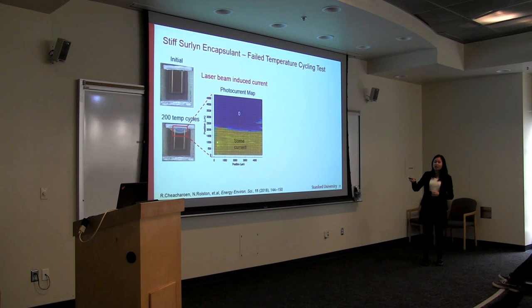I shine the light on and move the light along my pixel and measure the current that's coming out from that area. I can see that the area with rainbow fringes, the delaminated area, I didn't see any current, while the area that looks intact or brown perovskite has a lot of current. So I hope that I've shown you that using Surlyn caused a delamination problem in the package.